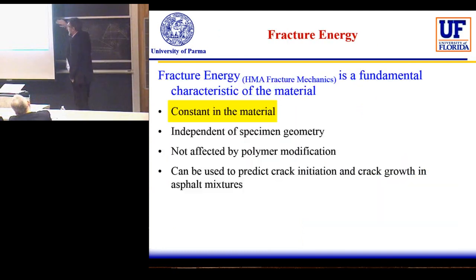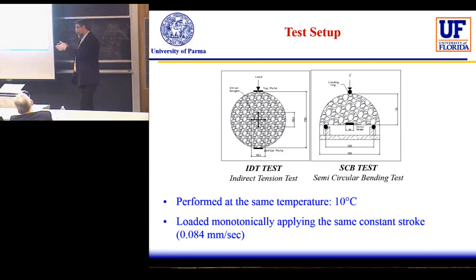So the first step was to verify the hypothesis that the fracture energy, in agreement with HMA fracture mechanics, is constant in the material. For that purpose it was fundamental to have the DIC, because we took pictures of the specimen during the test, and we calculated the stress and strain curve and the fracture energy at the point where we know that the crack will appear. Because we know where the crack appears, coming back in the pictures we can identify the point and make all the calculations. For that purpose two different test setups were used, the IDT test setup and the semicircular bending beam test setup. Again, same conditions that I showed before.